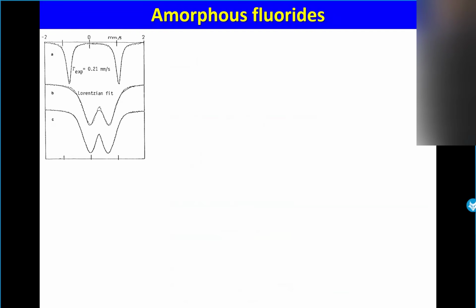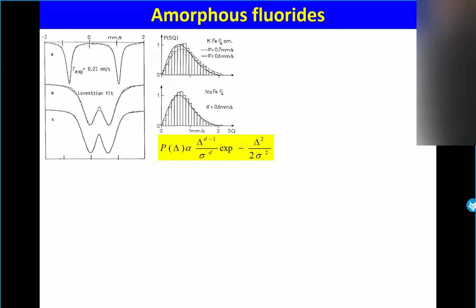As you can see, up top you have a spectrum of the crystalline sample. Below, you have the two spectra. If you put a single doublet with Lorentzian lines, you are not able to reproduce it. Why? You have an amorphous structure, so for each iron you have some typical environment. So you can put 2, 3, 4, 5. The idea is to put a distribution of doublets, a distribution of quadrupolar splitting.